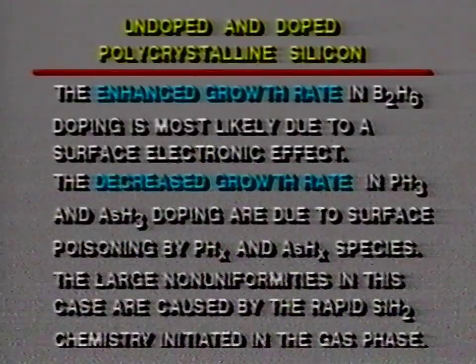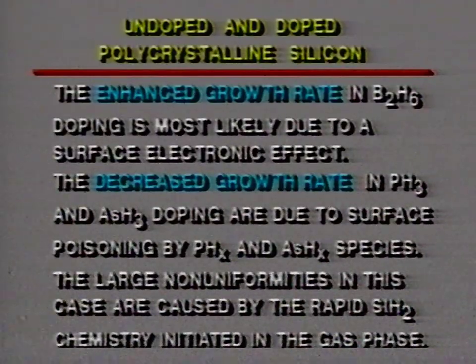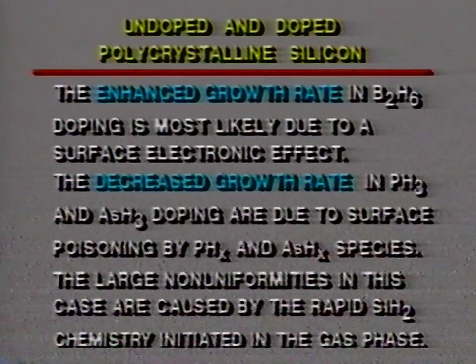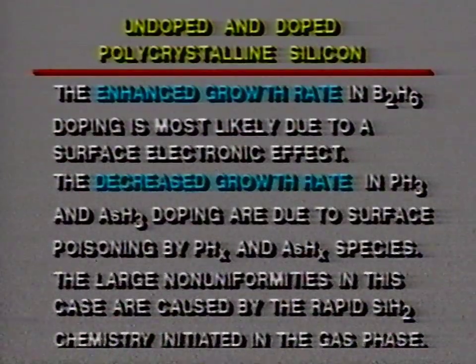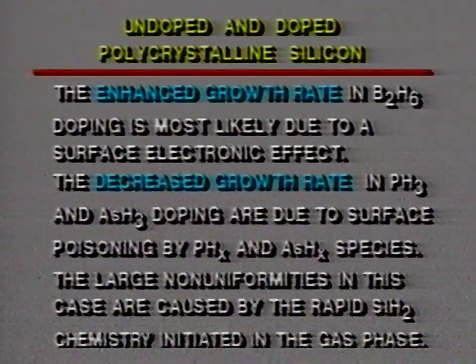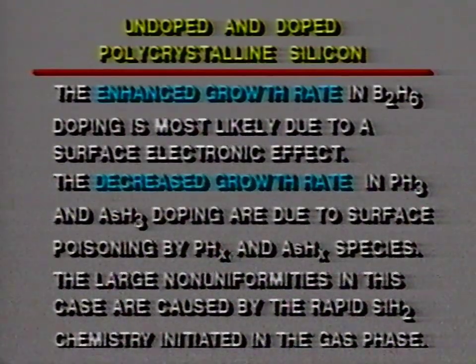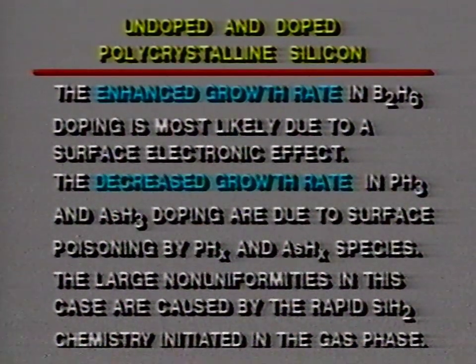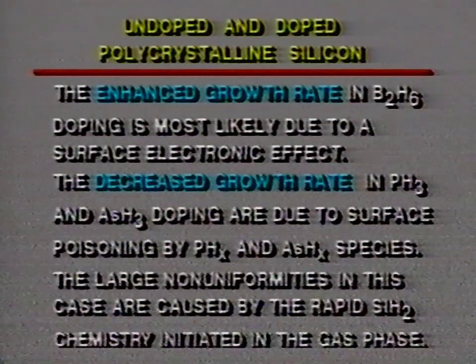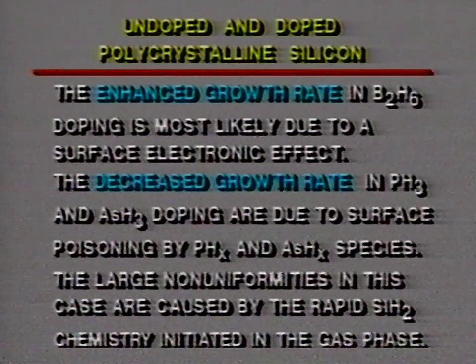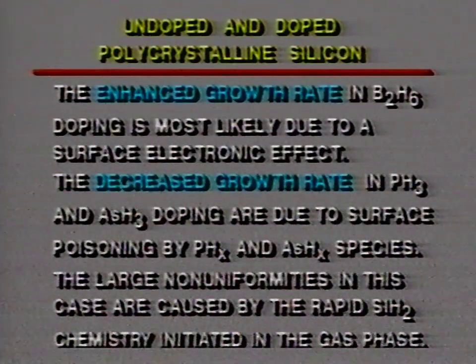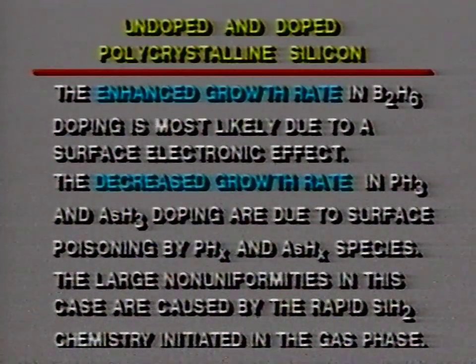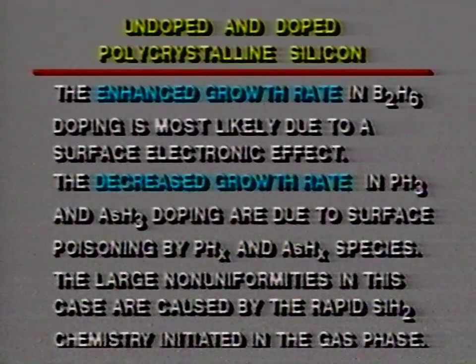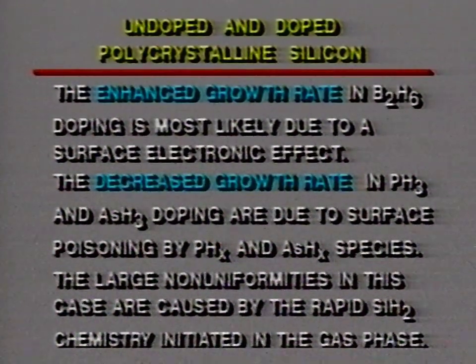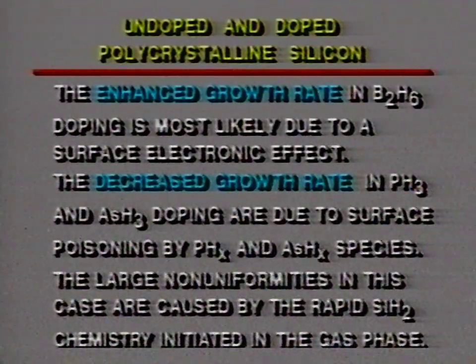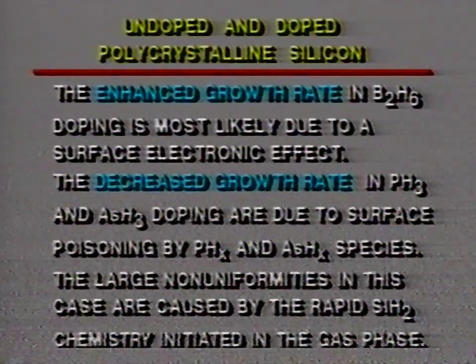We observe an enhanced growth rate in the case of diborane doping. And this is most likely due to a surface electronic effect. The decreased growth rates which we observe with phosphine and arsine generally are due to surface poisoning, and it is believed some PH sub x and AsH sub x species are involved in doing this. The large non-uniformities in this case are caused by the rapid disilane or silane or SiH2 chemistry, which is initiated in the gas phase, as we saw in one of the previous slides.